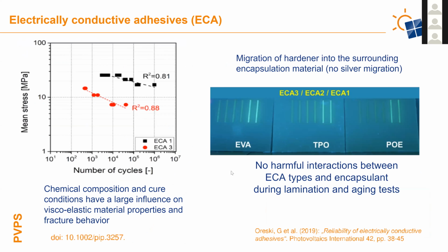In this study, migration of the hardener into the surrounding encapsulant material was the only migration observed. There was no silver migration out of the electrically conductive adhesives, and no harmful interactions between the ECAs and the encapsulants tested—EVA, TPO, and POE. That means they seem to be very well incorporated with these different types of encapsulants that are starting to be used more often.